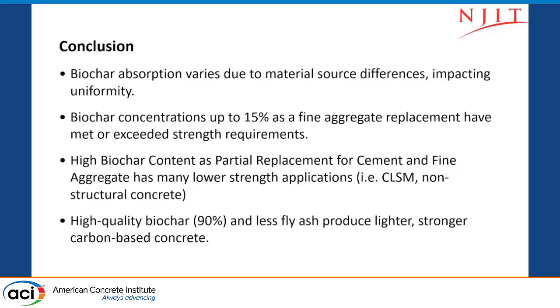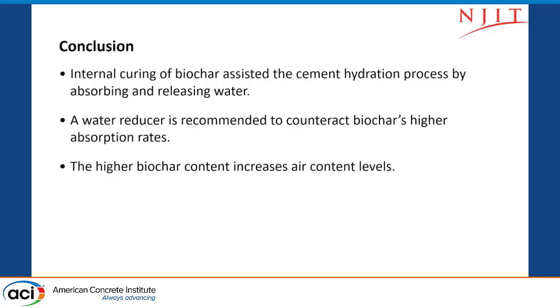Biochar concentration of 15% as a fine aggregate replacement has met or exceeded the strength requirements, and high biochar content as partial replacement for cement, which we are working on right now, and fine aggregate has many lower-strength applications. As we said, you can do the pantry and all of this stuff, non-structural concrete. High quality biochar, the 90%, and fly ash produce lighter, stronger concrete, and that's why I received it, and I'm pretty sure that it's going to be that. We have promising results with 80, but minimum 90 we didn't try yet.